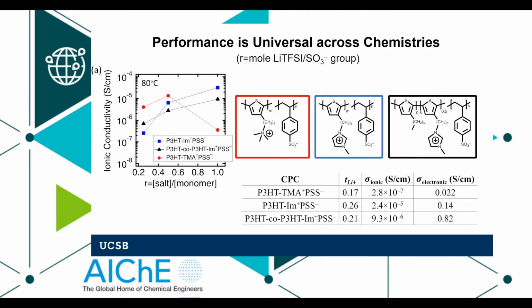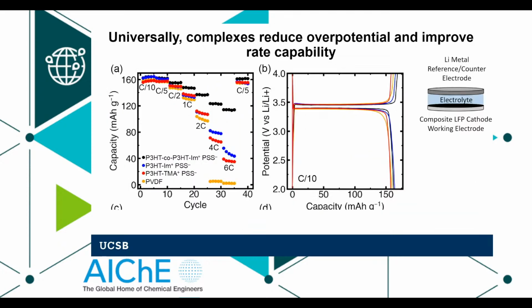And just to leave you with, that was a first attempt. There's a lot of space to play with this, right? What kinds of ionic liquids are we using as side chains? Which one of the commercial polyelectrolytes or homemade polyelectrolytes are we using as the partner here, right? And a lot of that has to do with trying to decrease the expense of these binders by throwing in commercial, relatively cheap stuff at least 50% of the solids loading. And this is just showing you that we're now starting to optimize that.